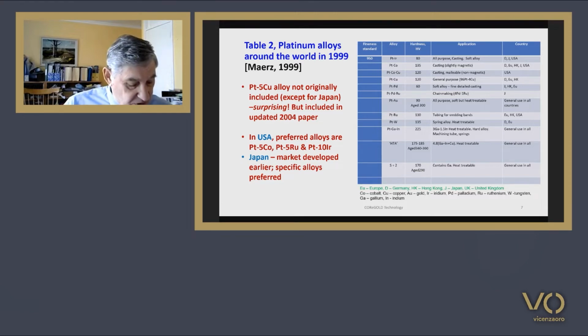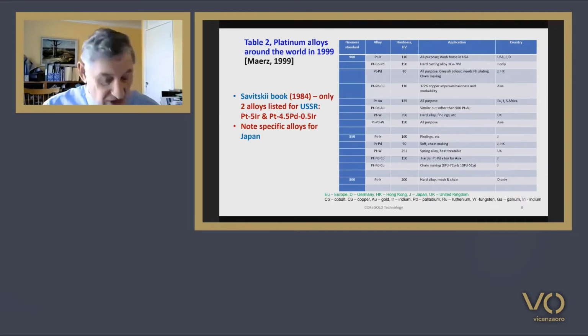Maerz does note that in the USA, the most common alloys in use are 950 platinum with 5% cobalt or ruthenium and 900 platinum, 10% iridium. However, in an updated version of this paper, the platinum 5% copper alloy has now been included. This table shows the rest of Maerz's table at 900, 850 and 800 fineness.